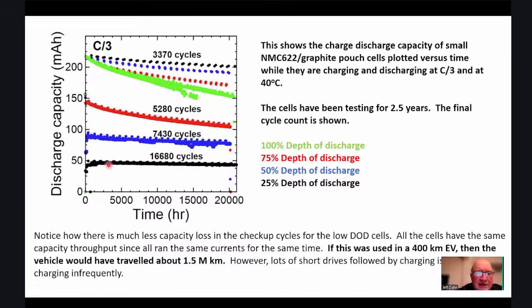So the black cells were operated most of the time with a 25% depth of discharge. So they're going from 4.1 volts down 25%. And the blue cells operated with 50% depth of discharge, and the red 75, and the green 100% depth of discharge. And I've listed the number of charge-discharge cycles obtained for these cells over this testing time.